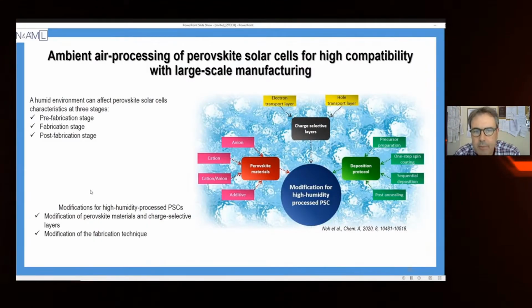When we are talking about ambient air processing of perovskite solar cells, I think that we have to refer here, to be sincere, that this is not the same as what is usually followed in a glove box. It means that the humid environment may affect several stages of perovskite solar cells, like the pre-fabrication stage, the fabrication stage, and the post-fabrication stage. So that's why we need to make some modifications for high humidity processed perovskite solar cells. It means that we need to make modifications to the perovskite material and charge selective layers. Also, we need to make modifications to the fabrication technique that we have to follow in order to finalize a perovskite solar cell.